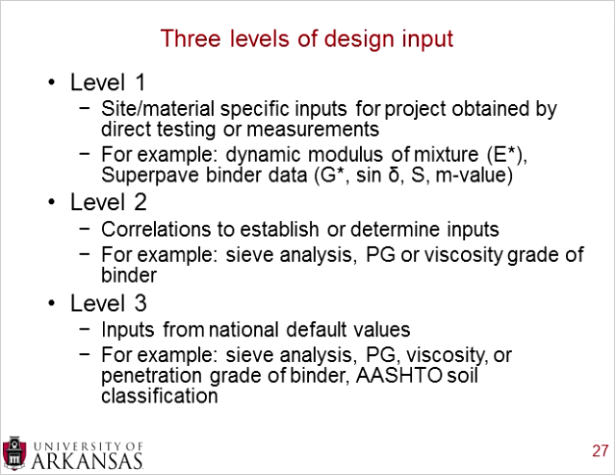And you also need to use Superpave binder data, for example, G-star, which is the complex shear modulus, the sine delta, where delta is the phase angle, the S, which is the creep stiffness, and the M value, which is the rate of change of creep stiffness versus time. So we have all these different measurements that we can take of the materials in order to get the best design.